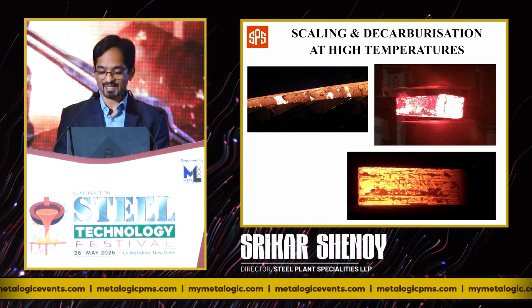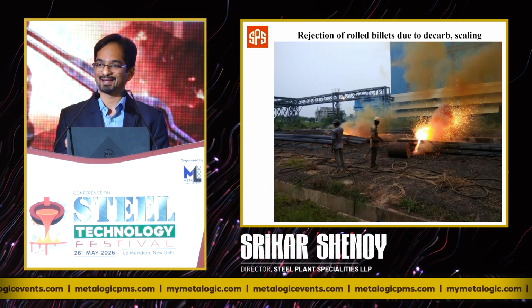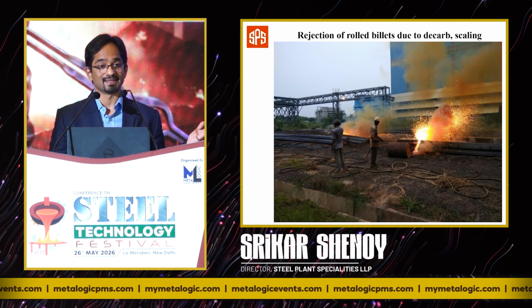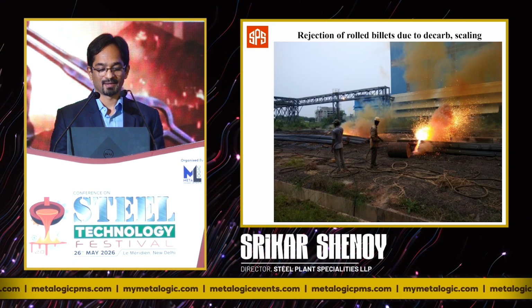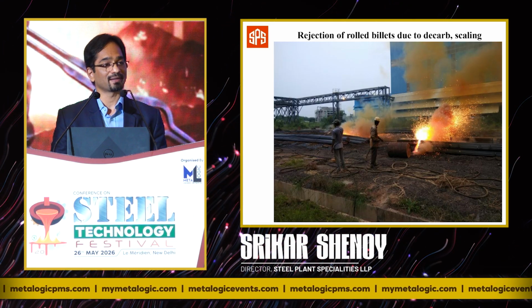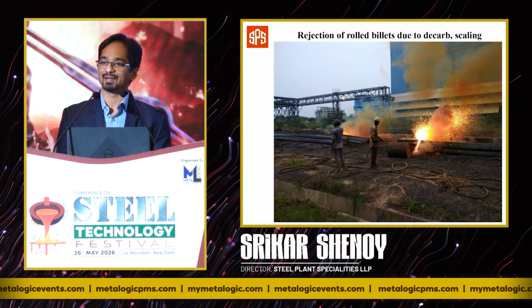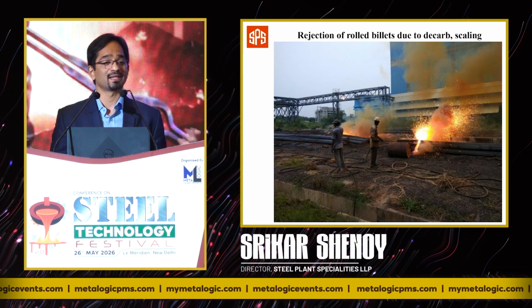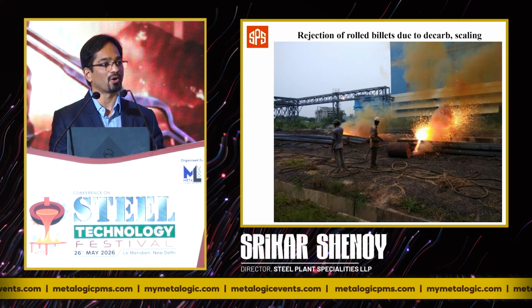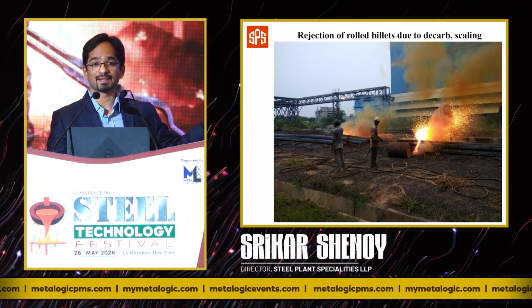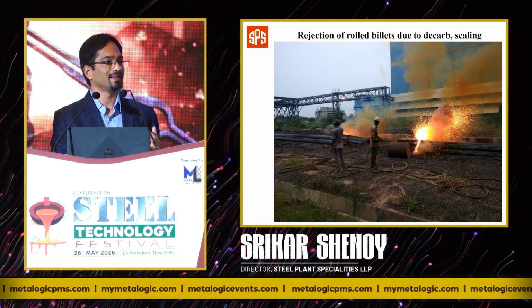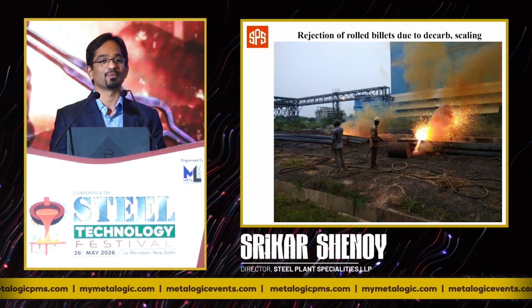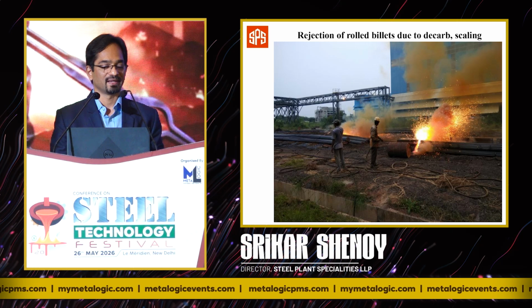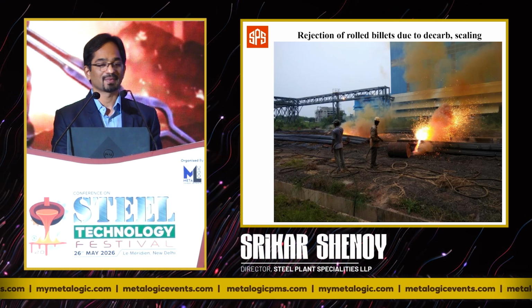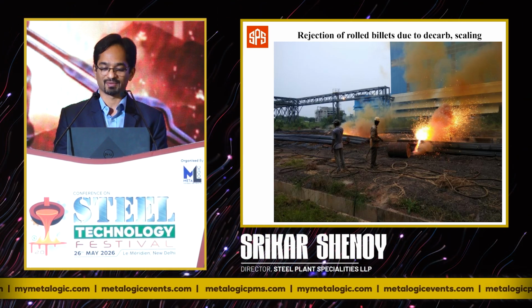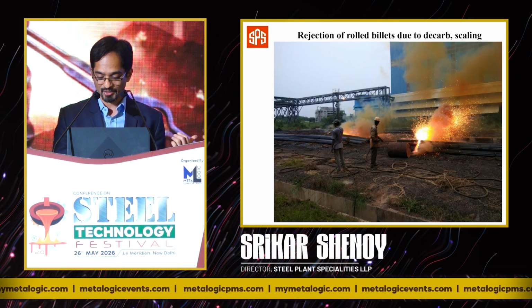What is the worst case scenario of scaling? This is a painful picture. The hot roll product is being gas cut to be fed into scrap. This organization has taken a lot of efforts to melt steel, to hot roll it, and they are gas cutting it and scrapping it simply because there was excessive decarburization, there was excessive scaling. If you have unplanned downtime, your billets are getting excessively heated in the furnace, which leads to all these losses.